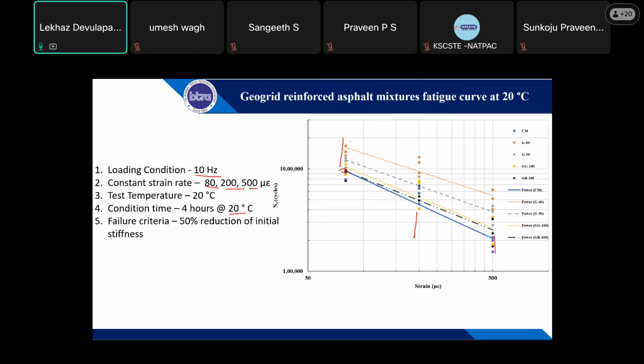And then with G60, it almost increased to 11 lakhs to 12 lakh cycles. Others also were a bit higher than the control samples. And if you see at 200 microstrains, the cycles are more than 10 lakhs for the G60, the polyester geogrid. When it comes to the glass fiber grids, it was also nearly 8 to 9 lakhs.